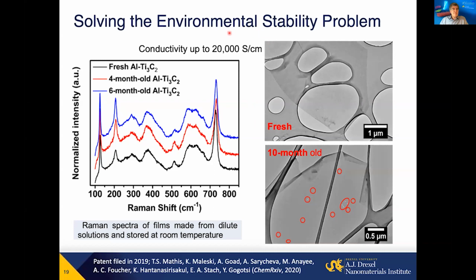We showed that by improving structure, it's possible not only to increase conductivity, but also to keep titanium carbide MXene, for example, with virtually no changes you can see from Raman spectra for months at room temperature in water. Moreover, even after 10 months storage, single layer flakes will only show a few pinholes. They're circled here in red, otherwise you won't be able to notice it in these few micron flakes. No oxide at the edges, no oxide at the surface.